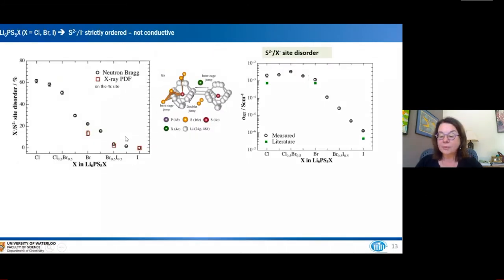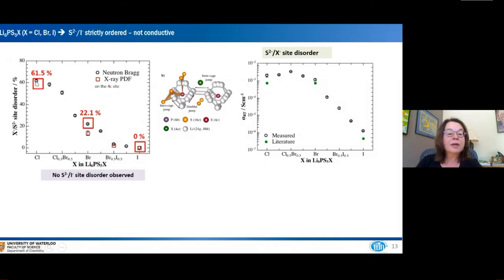This just shows, moving from chlorine to iodine, the extent of this disorder. So it's very high for chlorine, it's intermediate for bromine, and for iodine, it's literally zero - there's no site disorder. And that correlates, as I said, with very low conductivity, on the order of 10 to the minus 6 Siemens per centimeter. So it's extremely low.